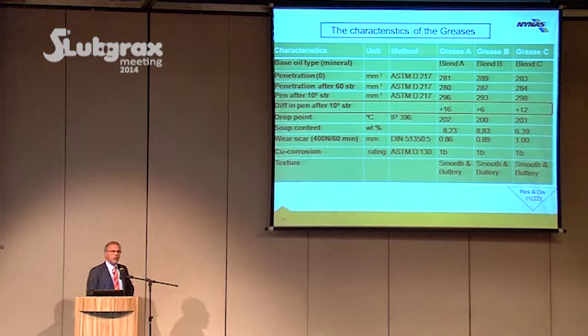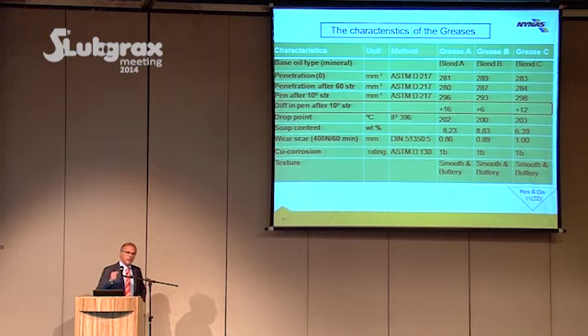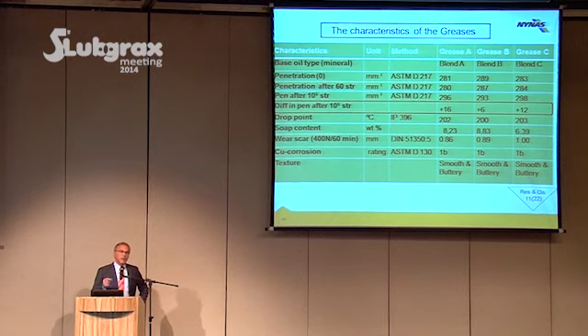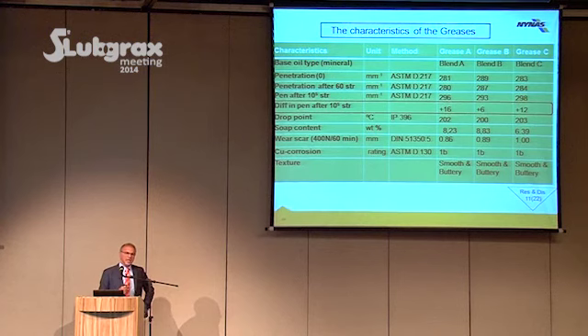And everything below 50, for instance, according to SKF, which is a bearing manufacturer, is acceptable. So we see here that all products are good, and we shouldn't take these numbers too seriously, because the repeatability of the test method is plus minus 8. So those are in the same range.